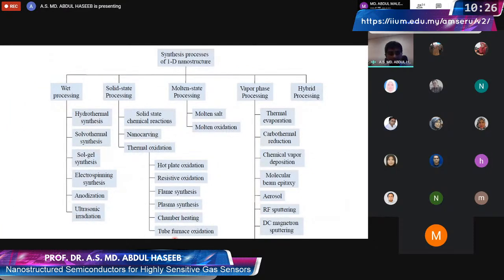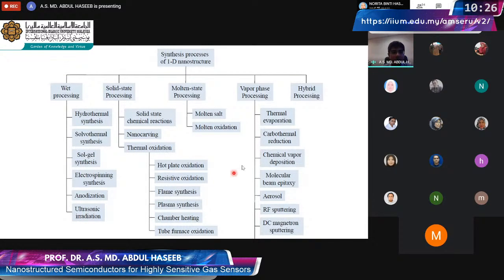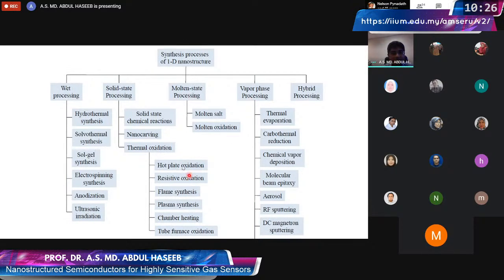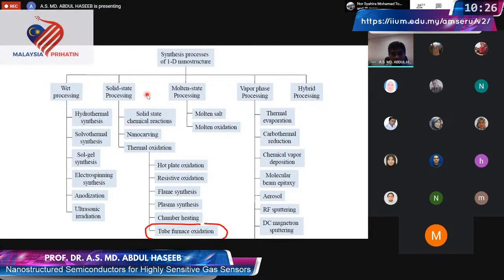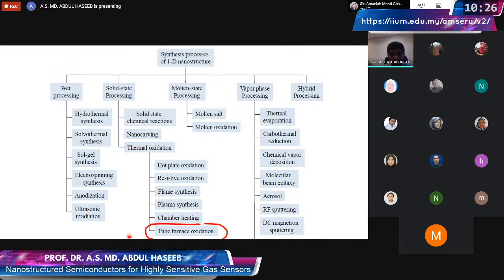There are a lot of techniques that researchers have been trying to produce 1D nanostructures. These are wet processing, solid state processing, molten state, and so on, vapor phase, etc., etc. And we have selected a process of solid state processing. And this is a very low tech. We just use a metal and then we oxidize them in a furnace. And of course, we have to optimize the condition, otherwise we don't get nanostructure, we just get thick scales or thick films of oxides.